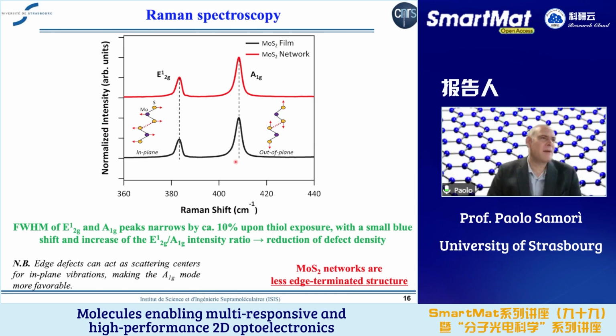We also exploited Raman spectroscopy, and in this case, we have been focusing on the E1_2g and the A1g peaks, and we saw that they narrow by 10% upon exposure to the thiol molecule, with a small blue shift and increase of the ratio between the two. This represents information about the reduction of the defect density. This kind of Raman spectroscopy was done in the group of Andrea Ferrari. So overall, we have less edge-terminated structure.